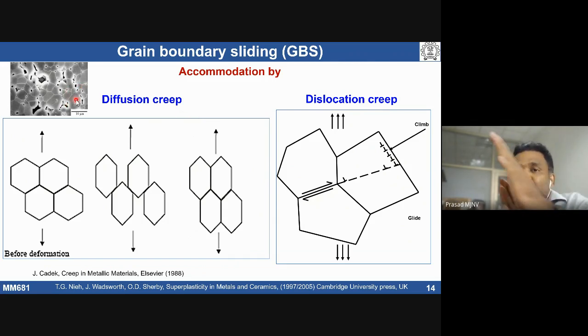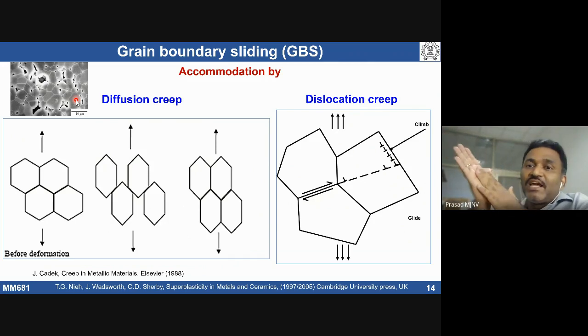Whenever there's grain boundary sliding, we do see wedge type of cavities. If some other mechanism simultaneously happens, like either diffusion creep or dislocation creep, that minimizes the cavity formation. When diffusion creep is accommodating grain boundary sliding, that can lead to a shape change of the grain. If dislocation creep is accommodating the grain boundary sliding, then it can lead to no change or negligible change in grain shape.